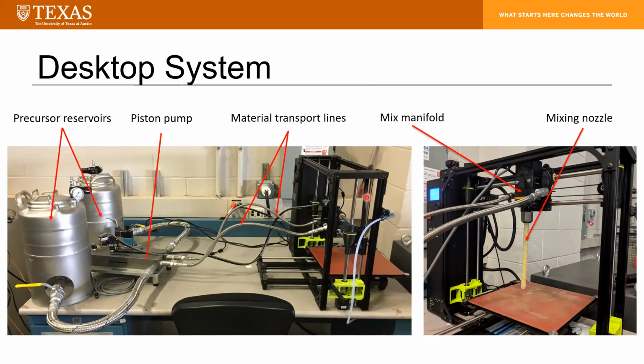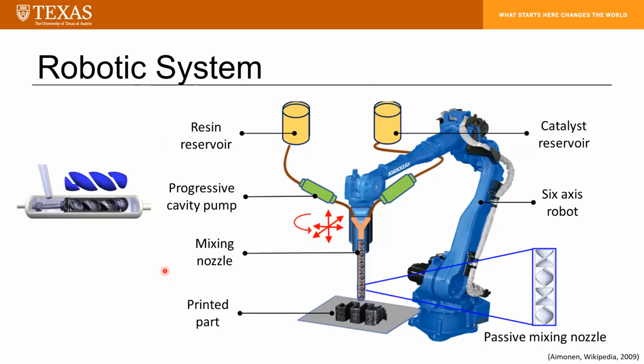And what we've done is we've taken an existing off-the-shelf FFF printer and converted it into our REAM system by replacing the original FFF printhead with our mix manifold and mixing nozzle. We've also converted the metering system actuation from pneumatic over to stepper actuation. And so this allows us to control the pumping system with the 3D printer's motherboard such that we get appropriate material deposition.